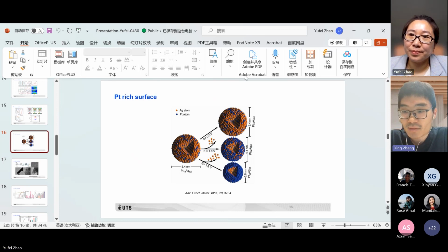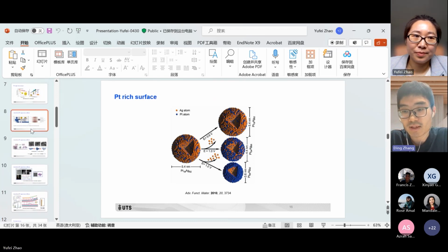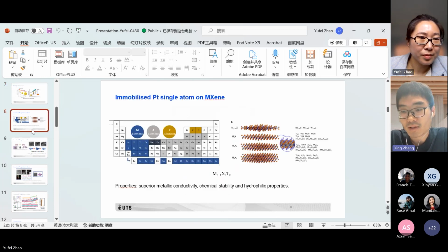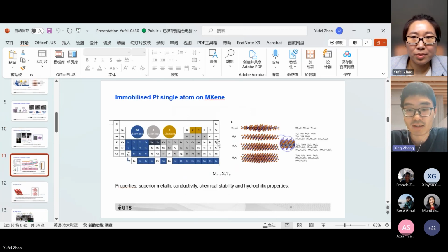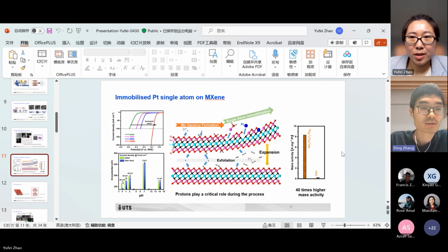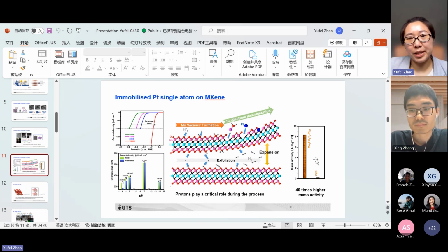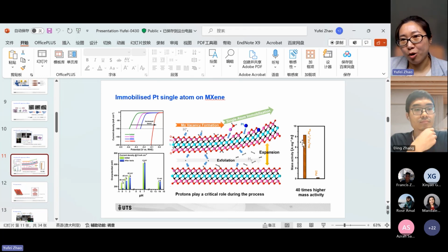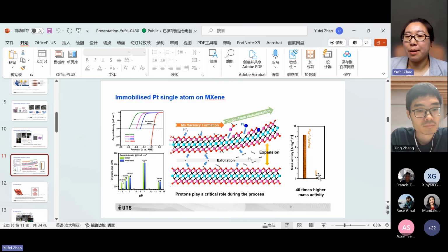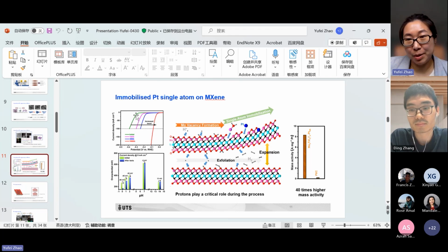So for platinum single atom on MXene, you reported the mass activity is 40 times higher than that of platinum carbon. But how about the activity per square centimeter of the electrode, or the overall yield of hydrogen, the productivity of hydrogen? The mass activity is high because the loading of the platinum on the MXene is quite low. So compared to the commercial platinum carbon, it's a really high mass activity. For the LSV readout, I cannot remember. The overpotential should be around 30 millivolts to achieve a current density of 10 milliamperes per square centimeter. So it's also very good.